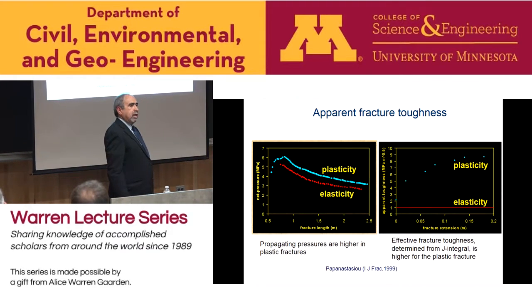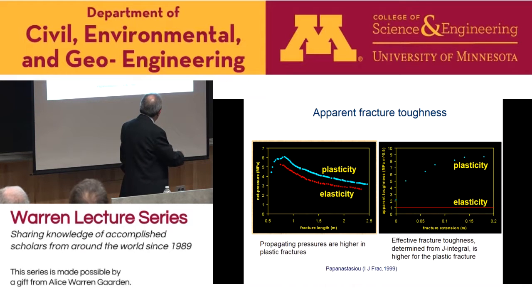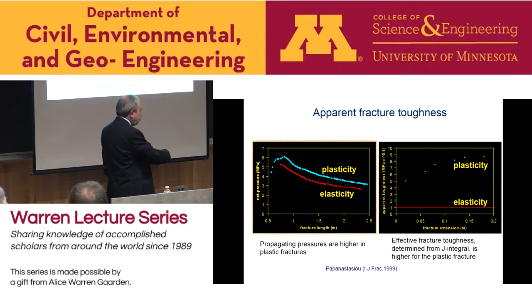But because the created fractures have different volumes, if you look at pressure versus time, what we measure in the field, we find that with plasticity the pressures are much higher than what elasticity predicts. The other thing with plasticity is that as the fracture grows, we have an increase in pressure for some steps until we reach this point, where the plastic zones are fully developed. After they are fully developed, the pressure drops, as you can see here. The other very important result is that we calculate the effective fracture toughness due to this plasticity.